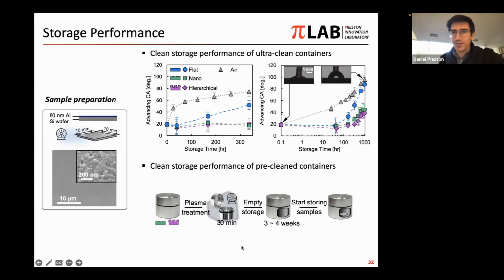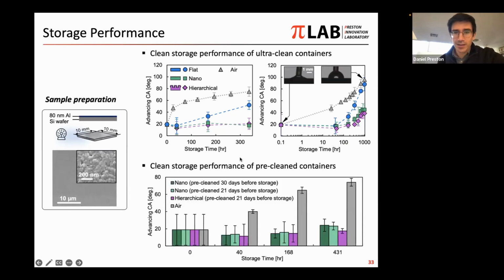And so to probe that question, we roughened the inner walls, plasma treated them for 30 minutes, and then left them empty for 3 or 4 weeks. No sample is inside. And then after 3 or 4 weeks, we started storing samples in these pre-treated containers. A month ago, for example, we treated it and then we just let it sit. Then we put the sample in, and we have sort of the baseline over here on the left. And we could compare that to, for example, the different types of containers that had been pre-cleaned either 21 or 30 days before storage of the sample.